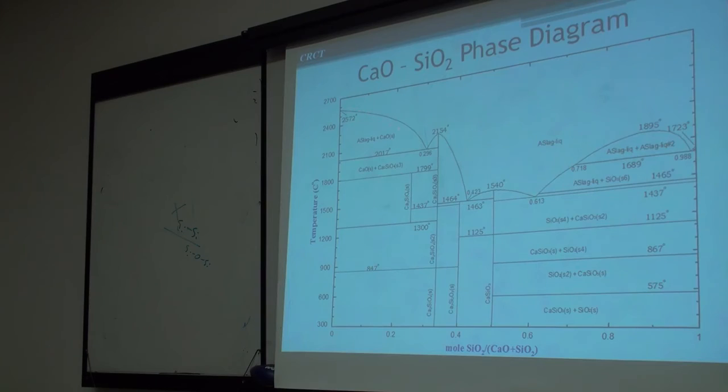You see this liquidus dropping quite quickly on this scale, but this is several hundred degrees. Were this compound not here, if you just take this compound out of your FactSage calculation and just continue to calculate the metastable liquid, it drops way, way down, because the activity of calcium oxide is going virtually to zero.